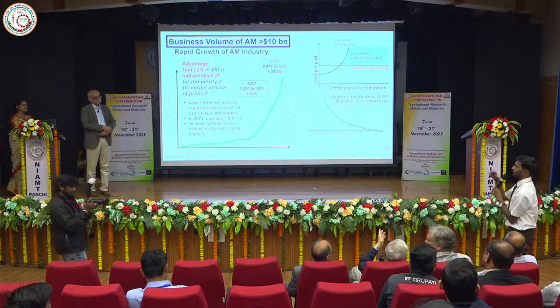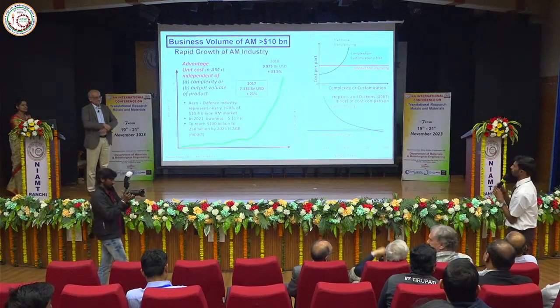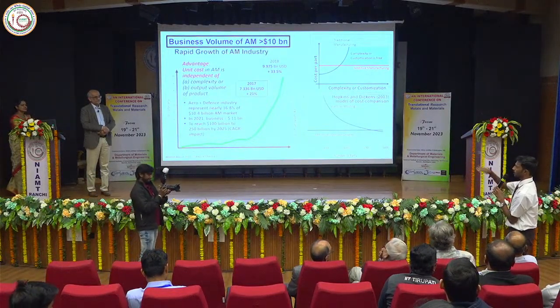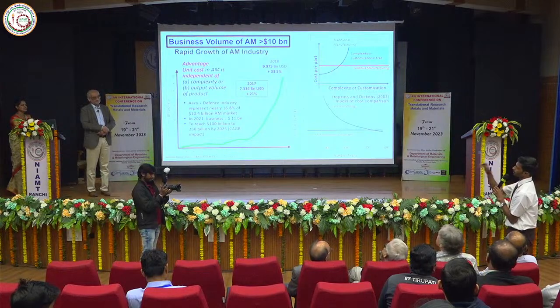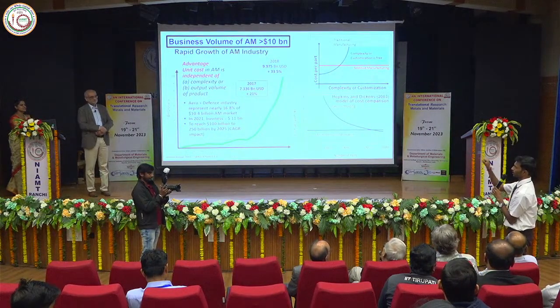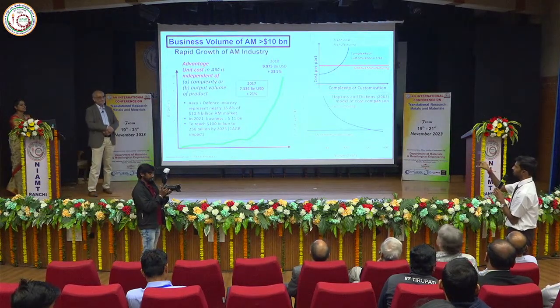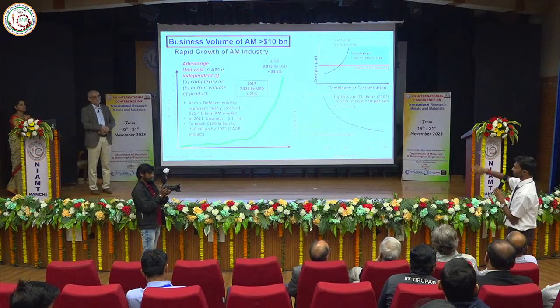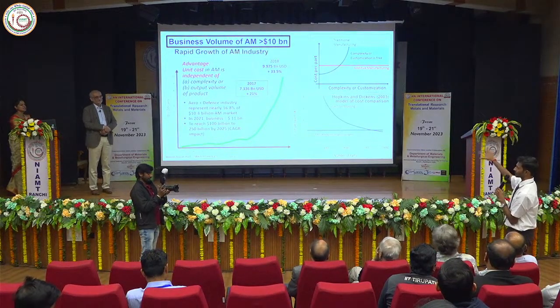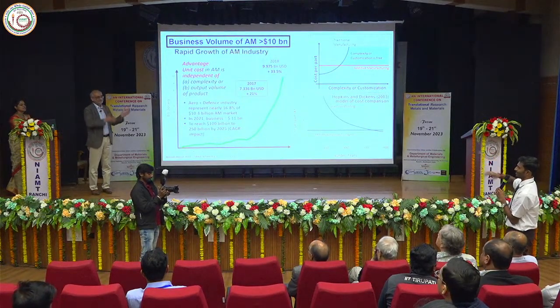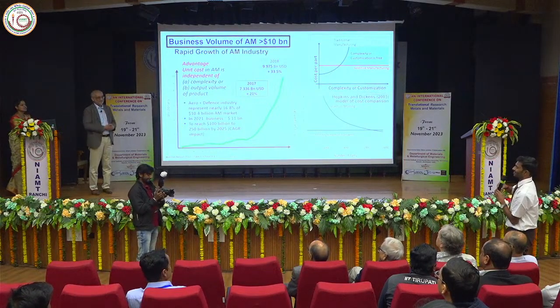Sir, in Inconel 718, IN 718, which we use for space research, mostly the superalloys, you have made a layer of silicon or aluminum, the silicon layer. What kind of bond does it make with the austenitic alloy? Because the austenitic alloy which we are using will withstand up to 1200 or 1300 temperature. It's an FCC, whereas the other one is diamond cubic. So how do they talk to each other?